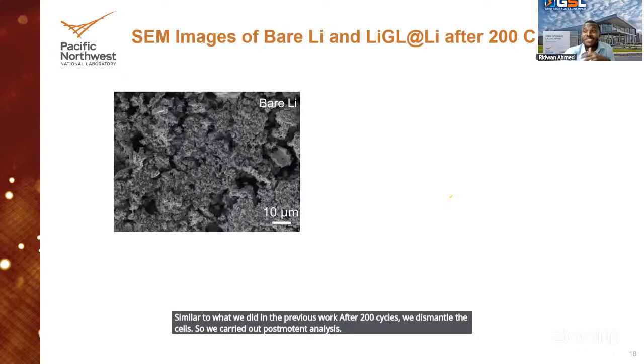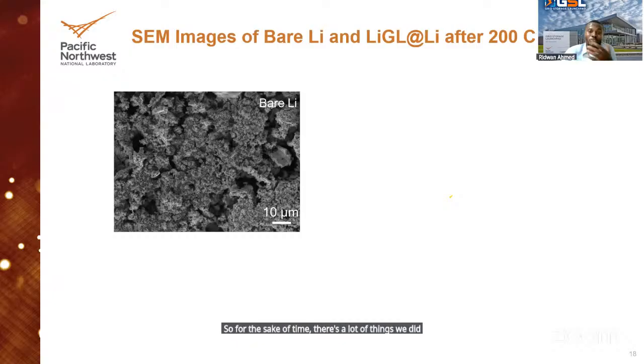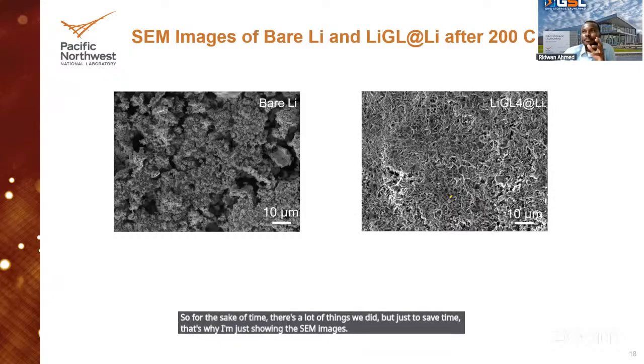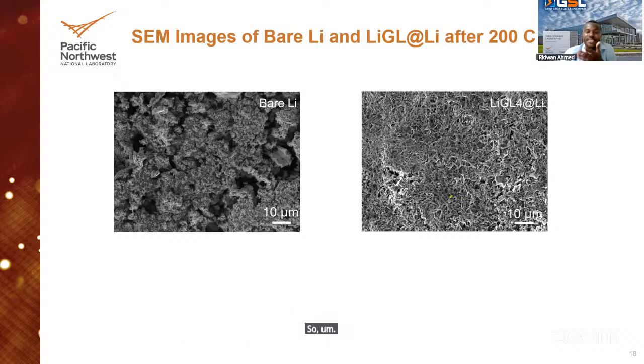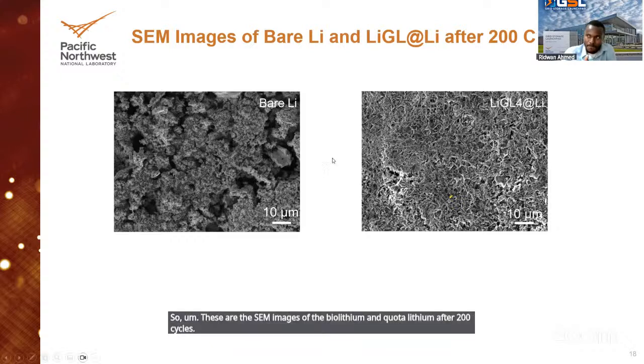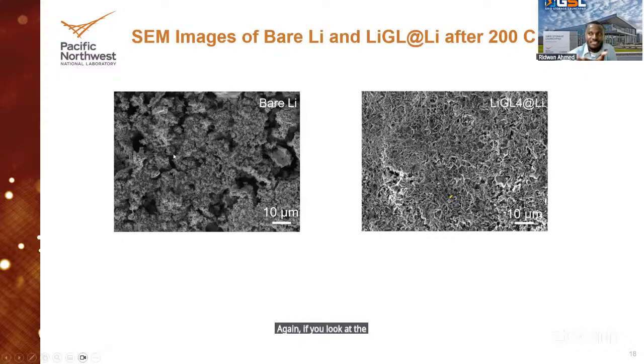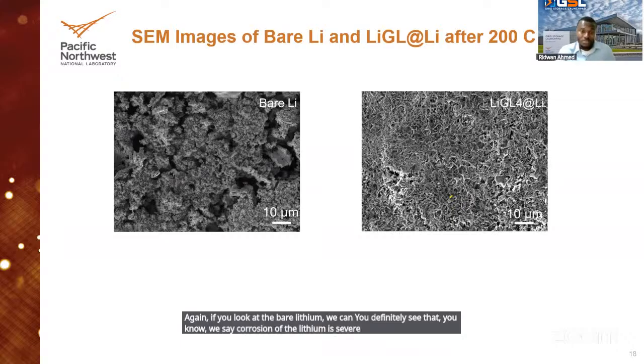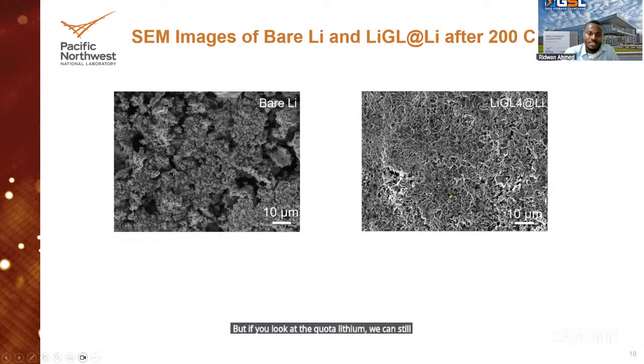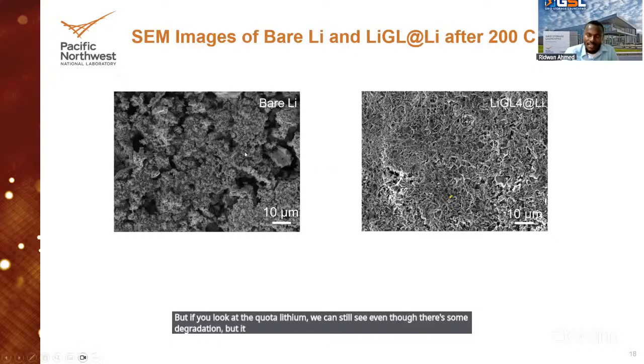Similar to what we did in the previous work, after 200 cycles we dismantled the cells, so we carried out post-mortem analysis. For the sake of time, there are a lot of things we did, but I'm just showing the SEM images. These are the SEM images of the bare lithium and coated lithium after 200 cycles. If you look at the bare lithium, we can definitely say the lithium is severely corroded or degraded. But if you look at the coated lithium, even though there's still some degradation, it's not as severe as that of the bare lithium.